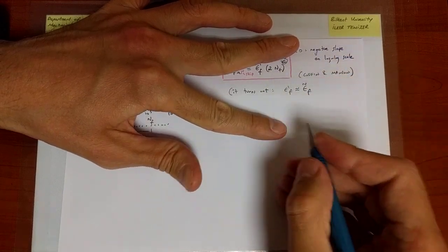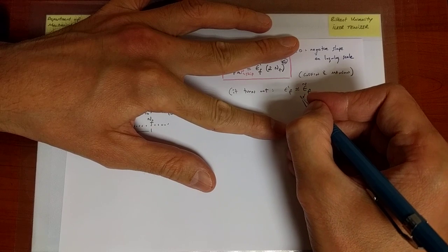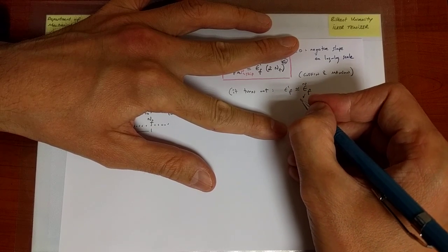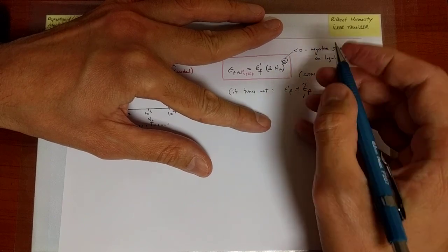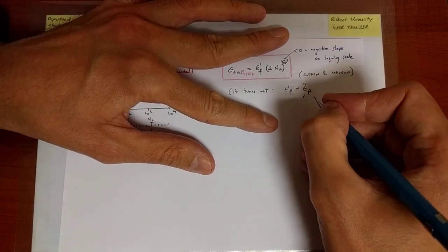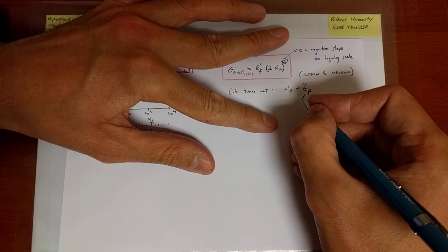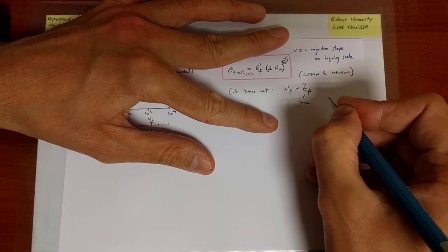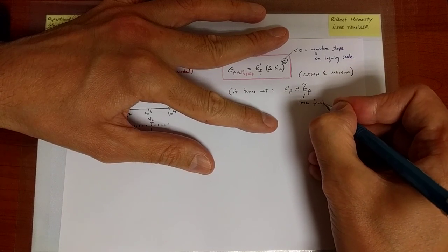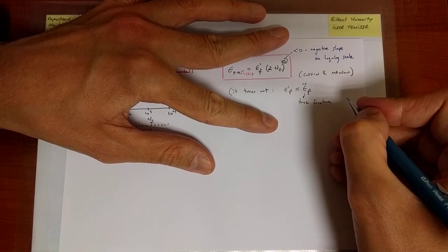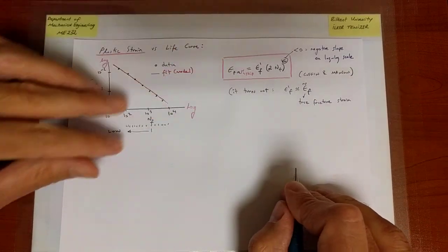It does make sense that it's associated with the uniaxial stress-strain curve failure value, because if failure occurs at the very first cycle, or in fact even the first half cycle, then it makes sense that epsilon'_f should be associated with that failure value, and indeed experiments are supportive of that observation.